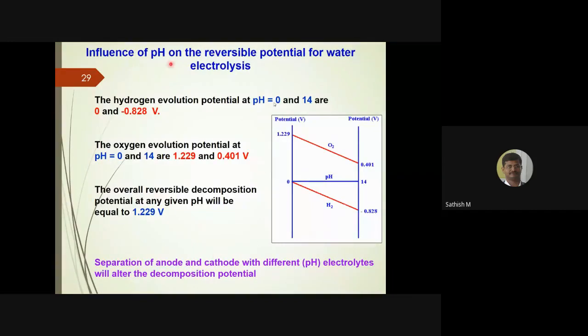This is another flow chart you could see here. This is pH 0, and this is pH 14. This is the hydrogen evolution potential, and this is the oxygen evolution potential. At highly acidic pH, the hydrogen evolution is 0 but the oxygen evolution is 1.23. As you move the pH from 0 to 14, at any point if you draw a line from here to there, there will be a hydrogen evolution potential and an oxygen evolution potential. If you add these two, you obviously end up with 1.23. You cannot escape this; 1.23 is a minimum.